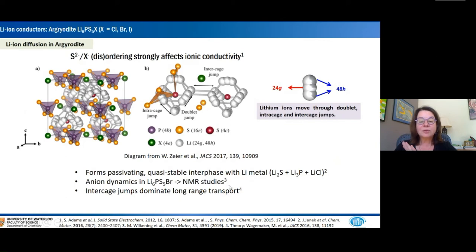So these materials have been studied extensively. A lot of these studies are shown here. And the best thing about Argyrodites is that they also appear to form a fairly good interface with lithium metal, as shown by Jürgen Janek, with these being the items that form the passivating interface.